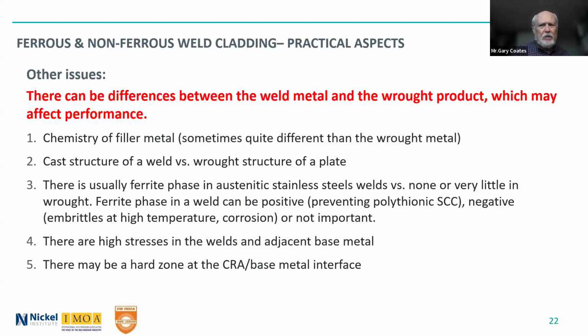Let's talk about a few other issues here. One is there can be differences between the weld metal and the wrought material, which may affect the performance. Of course, the chemistry is one of those things. It's sometimes different than the wrought material. So if somebody says, I want alloy, let's say C22, nickel as the CRA layer, the chemistry in that case is very similar, but it is a little bit different. Other alloys, it can be more different. But on the other hand, if you're welding two pieces of, let's say, C22 together and use the C22 filler metal, well, you already have it there. So usually that's not an issue. It can be an issue in a few very, very unusual cases, but it is something to check if somebody is asking for clad material of a certain alloy.